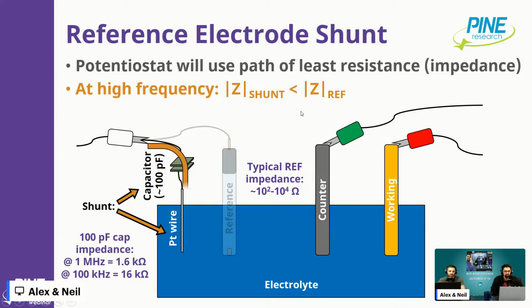So at high frequency, like a megahertz, 1.6 kilo ohms of impedance across this capacitor is less than, let's just say, 10 to the 4. It's less than 10 kilo ohms. So the potentiostat is going to not measure my reference electrode. Now, you could think this is bad, perhaps, but the reality is that the reference electrode at high frequency is causing problems. So I'm bypassing those problems. I'm getting rid of those problems.